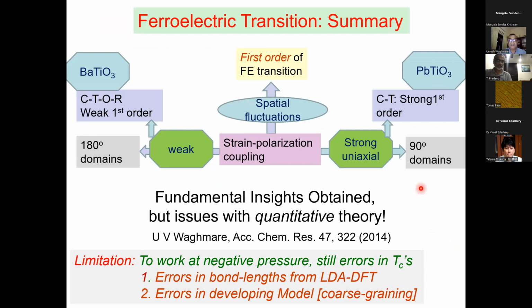So to summarize this part of my presentation, what we showed, again, I didn't go into those details, is the fundamental coupling here is the coupling between strain and polarization, which is what is responsible for piezoelectricity, by the way, because the electric field causes strain in piezoelectric effect. And this coupling is responsible for first order transition, and also it is weak in barium titanate, and that's why you get a very different behavior of domain walls, whereas it's very strong in lead titanate, and you get 90-degree domain walls which are stable, and of course cubic only one phase transition.